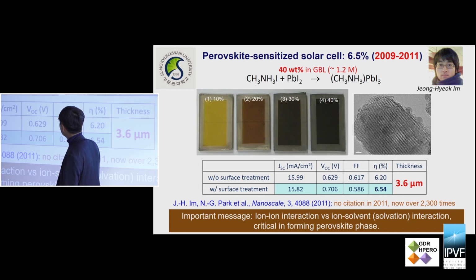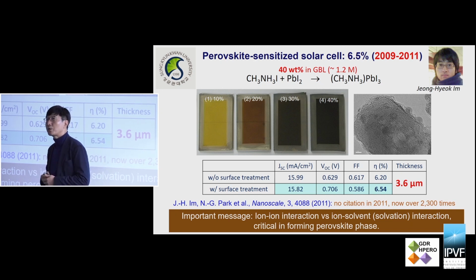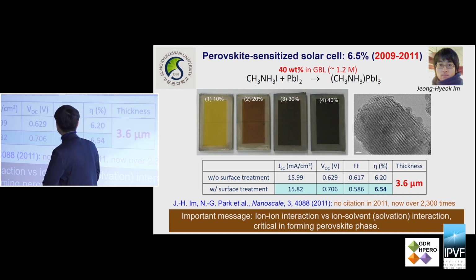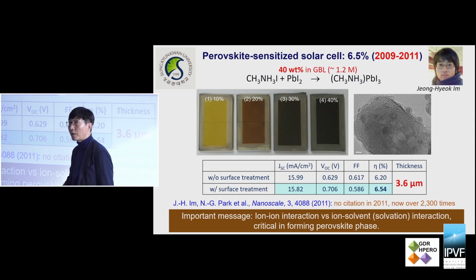So we changed the concentration of this precursor solution, and we found that 40% is almost the supersaturation concentration in the polar aprotic solvent here. And the 40% reproducibly produced the perovskite film. The first version of this perovskite solar cell is based on the quantum dot morphology of perovskite sitting on the titanium oxide surface. And then we reported an efficiency of 6.5%.